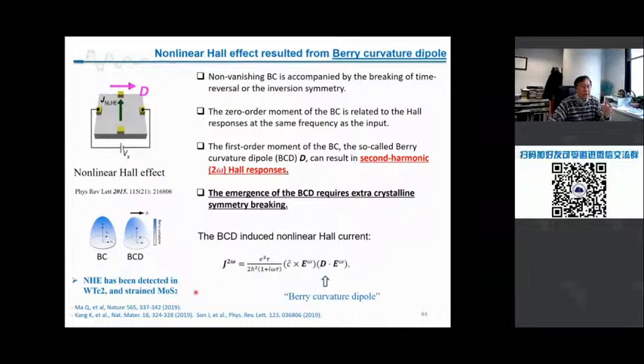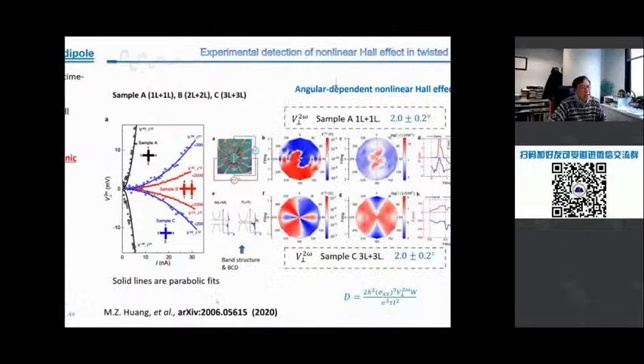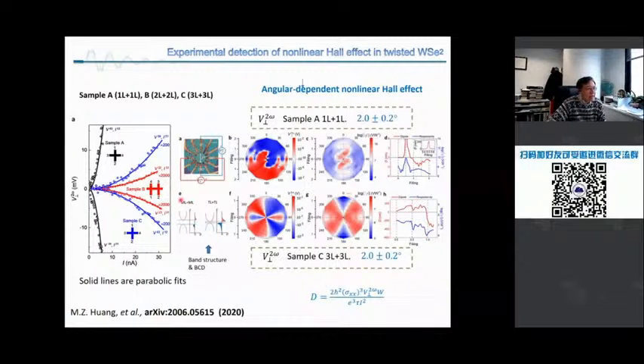Okay. The nonlinear Hall effect is normally weak. Previously, people discovered it in WTe2 and strained MoS2 and so on. Right? And the nonlinear Hall effect voltage that we detected is much higher than those discovered in these materials. It is 6 orders of magnitude higher than those materials. Very exciting. So I will show you the experiment data quickly.